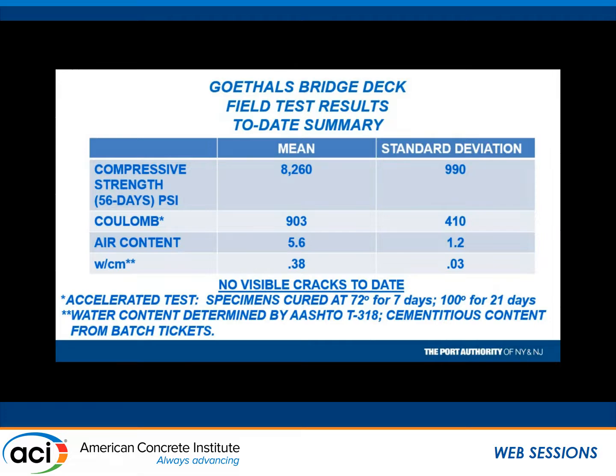And there was the water cement ratio that we actually got, and that's the other thing that we do, okay? We do use the microwave test in the field with every sample that we take to determine water content, and people say that test method doesn't work, it's whatever. There's several stories out there. We've been using it for 20 years, and it does work.